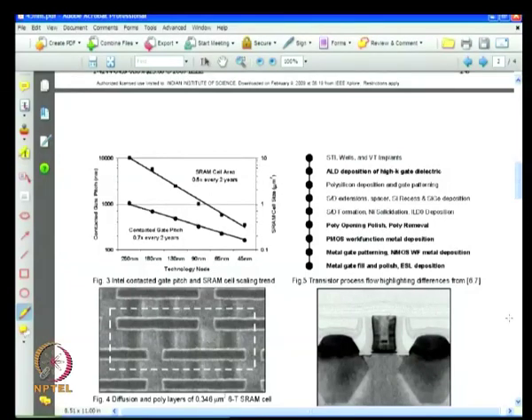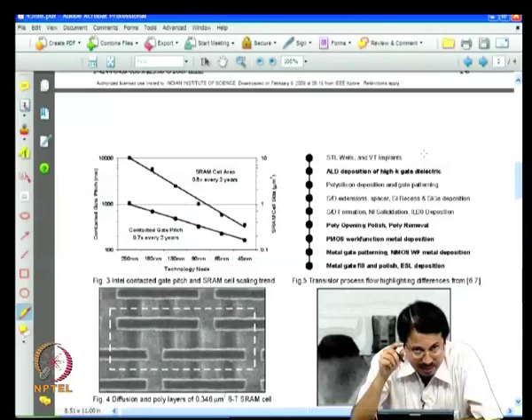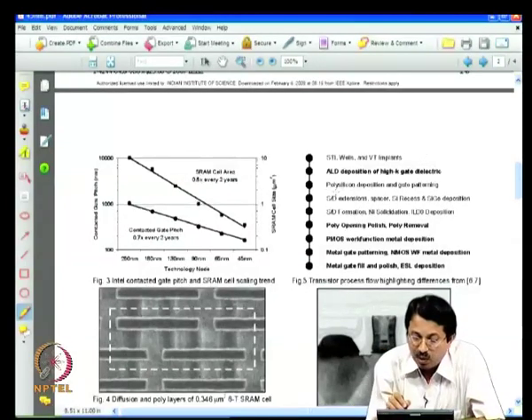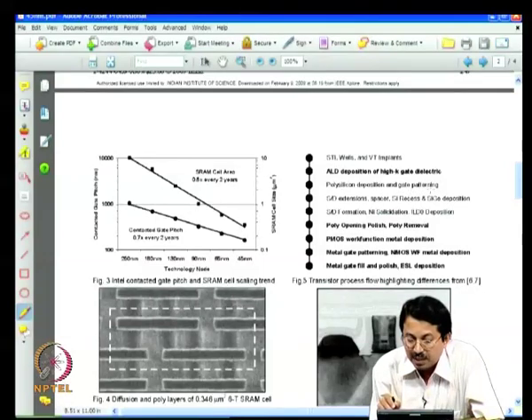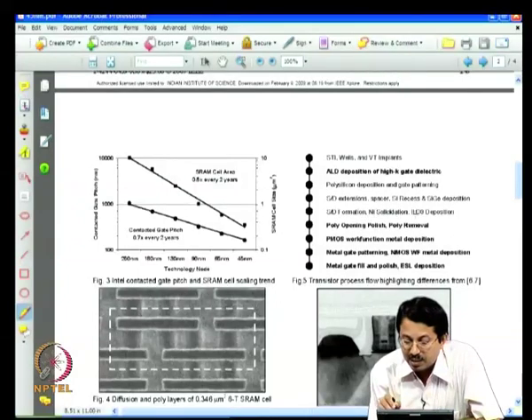So what is the typical process flow? They do STI, shallow trench isolation, wells, and adjust the VTs. They deposit the high K gate dielectric using atomic layer deposition. ALD is atomic layer deposition of that dielectric. They do a disposable metal gate, remember the discussion that we had. So polysilicon is done as usual: gate patterning, source drain extension, spacers, source drain formation, nickel silicidation, and then you deposit an insulator. Then poly opening, you etch back the poly, and the poly is removed. That is what we mean by disposable metal gate.